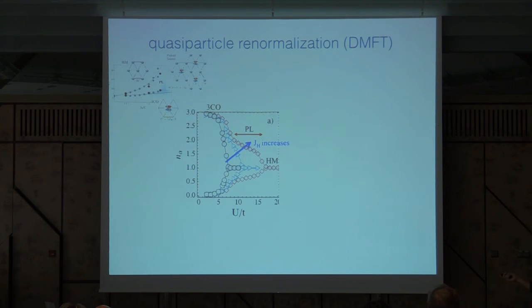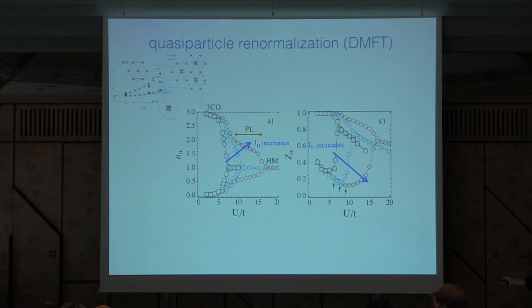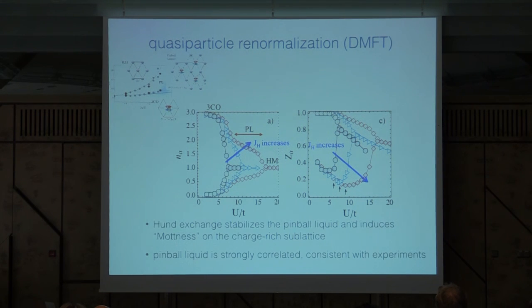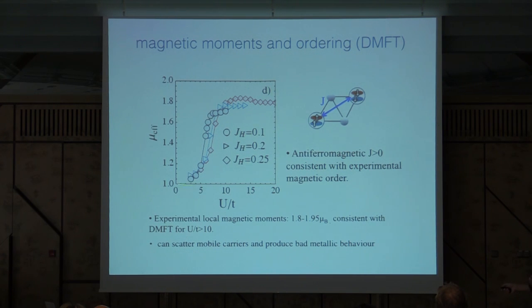With dynamical mean field theory, we can calculate the quasiparticle renormalization, which is this Z parameter. What we see is that in the whole pinball region, when you increase the Hund's coupling, you stabilize the pinball liquid, and it has very strong correlations on these pin sites. The renormalization is about a factor of 10. Last, we can calculate the effective magnetic moment. This is again a scan versus the strength of the local Coulomb interaction. If you put no local interactions, the effective moment is 1. But then at some point you cross the boundary to the pinball liquid, and it shoots up and reaches values of around 1.8, which is exactly the one that is measured in experiments.